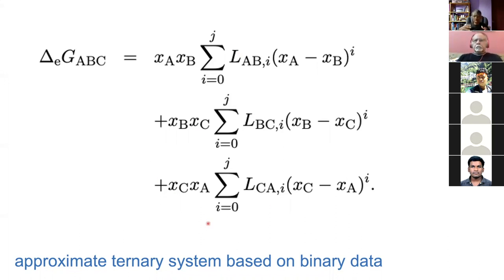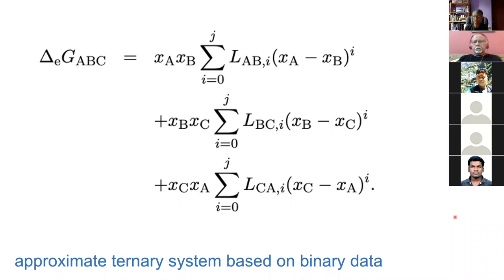Going from binary into a ternary system involves an approximation, since we are only using the end-member binary interactions. Nevertheless, it's a good approach when you have no ternary interaction data — only interactions between C and A, B and C, and A and B. This is the first approach when data are lacking, and if your ternary calculation turns out to be incorrect, that indicates you need to generate experimental data, because the entire calculation relies on experimental data.